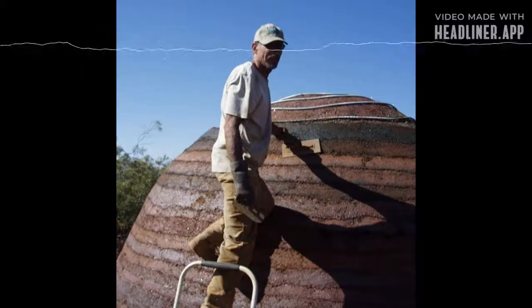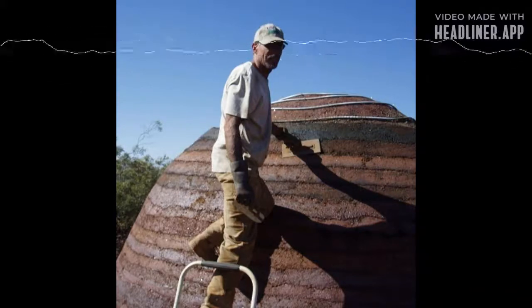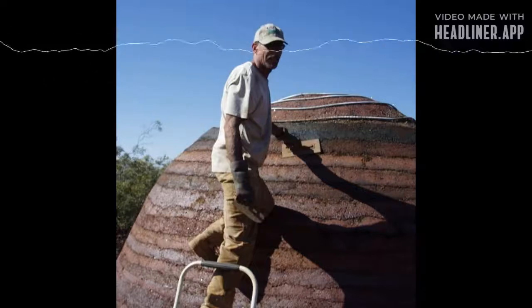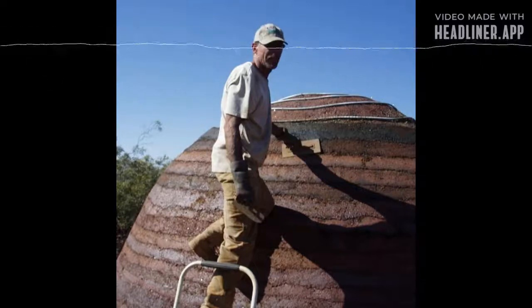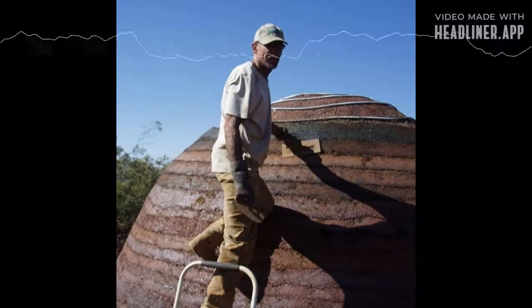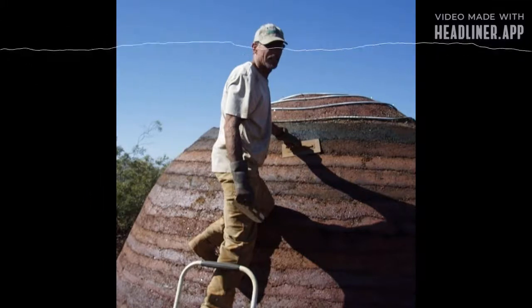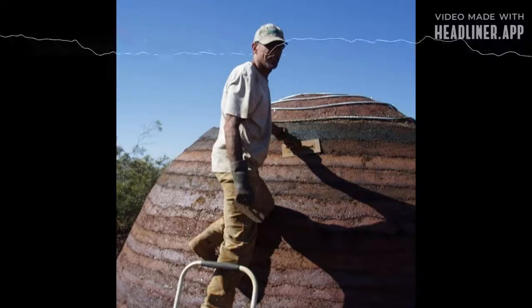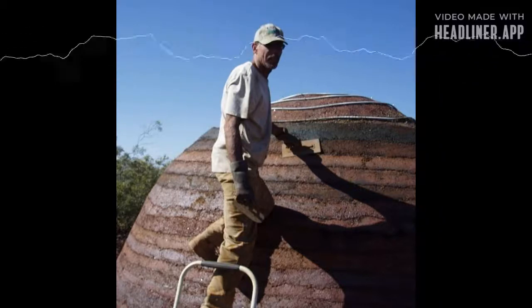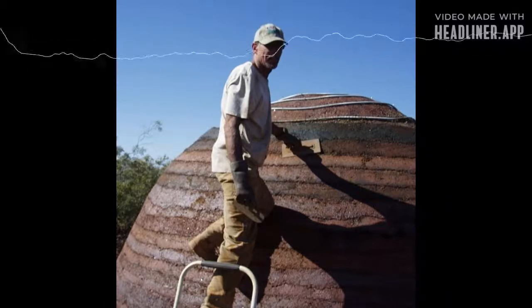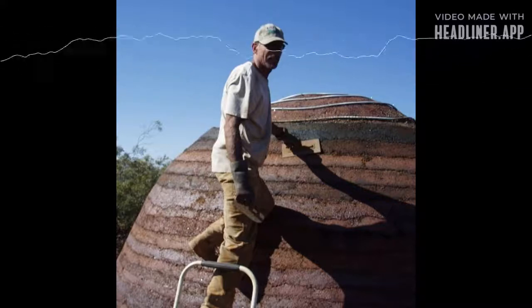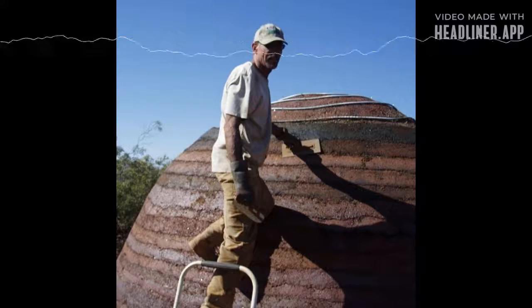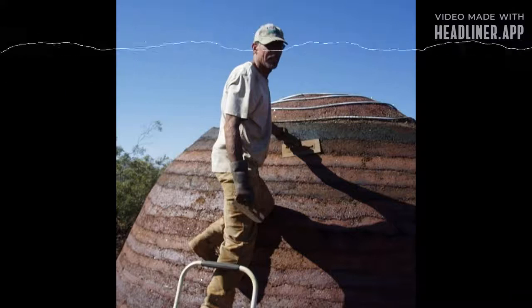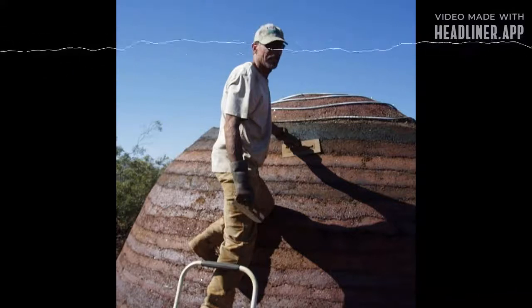We used Ferrock as the binder, an iron-based binder, and crushed glass bottles as our aggregate, and our only aggregate. No sand, no gravel. Ferrock can bend more without breaking, and it can take more stress without bending. In other words, it holds together more cohesively, and they call that flexural strength. And that is also related to its greater toughness and its greater crack resistance. So even if there is a little crack created, Ferrock will not break apart as readily as Portland cement.